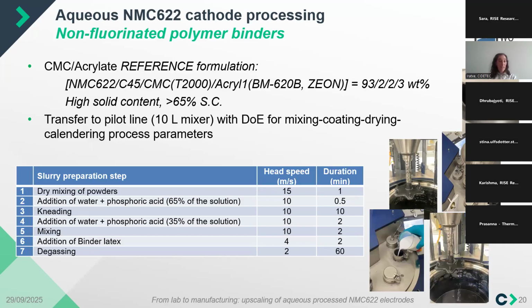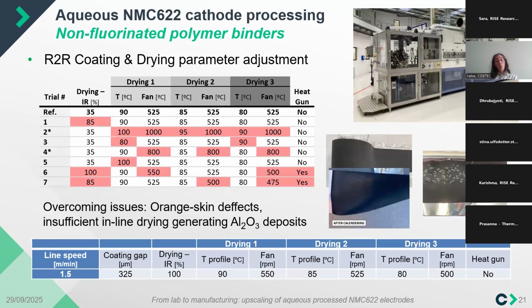Also to show mixing steps, going into a 10-liter mixer. In this case, a whole matrix of drying conditions, in another of the coating lines we have at Cidetec, which has a longer drying zone and an infrared drying area at the beginning. The others are air nozzles, a different type of drying that you can find in coating lines from conventional ovens too.